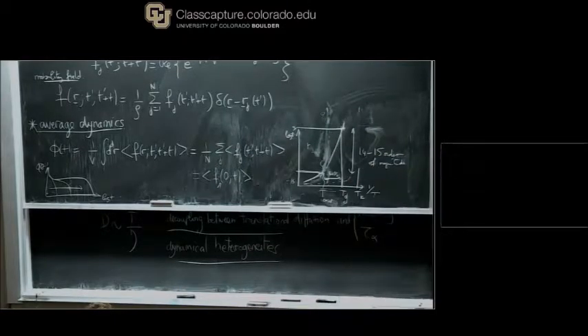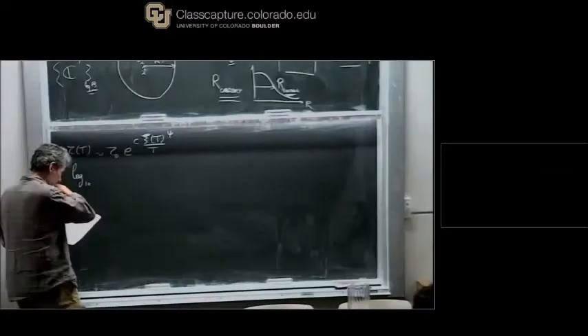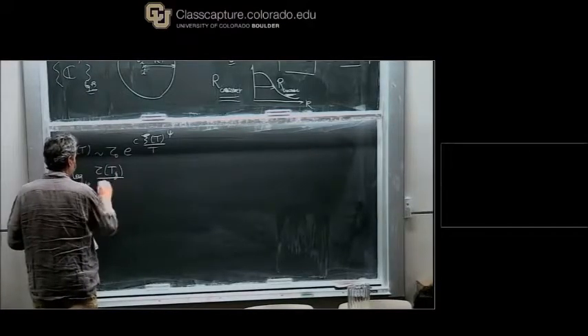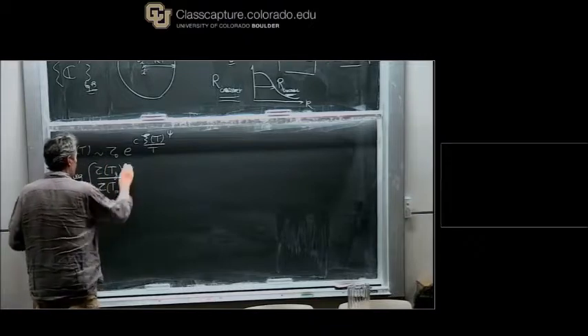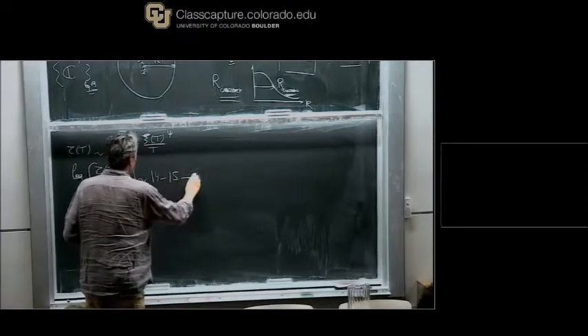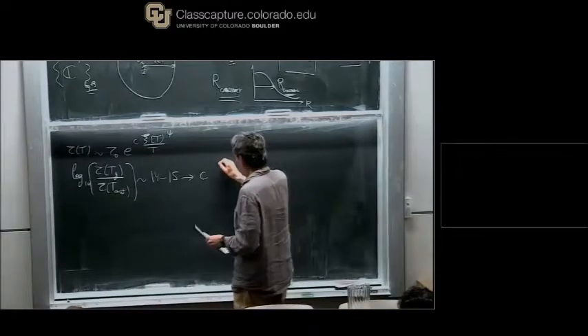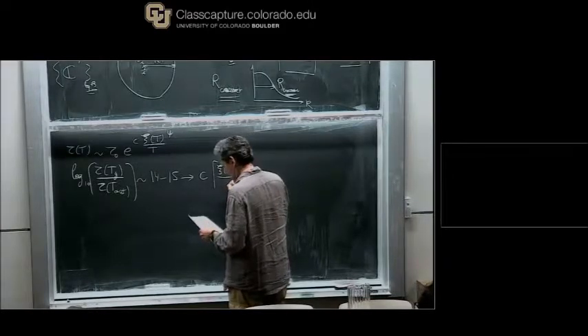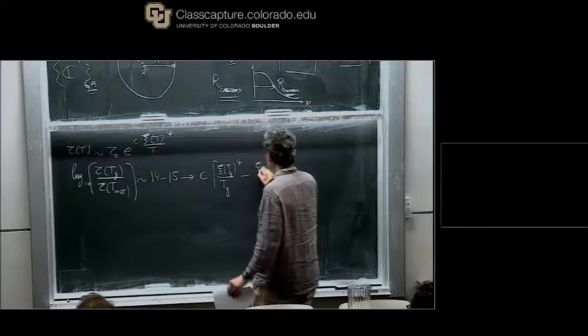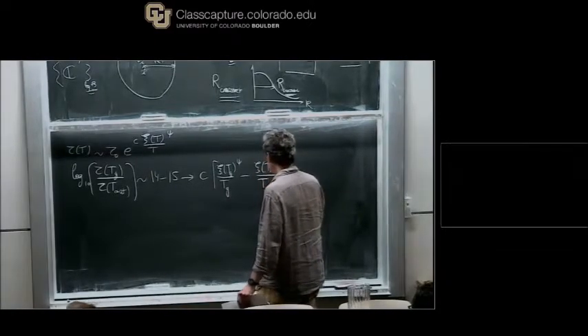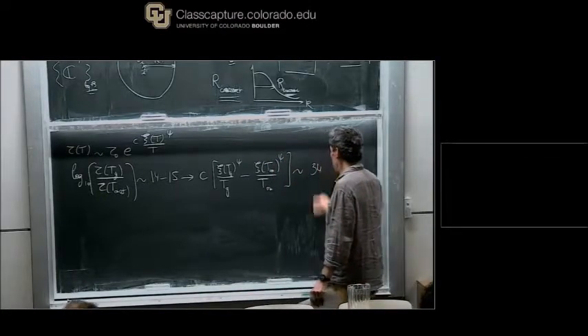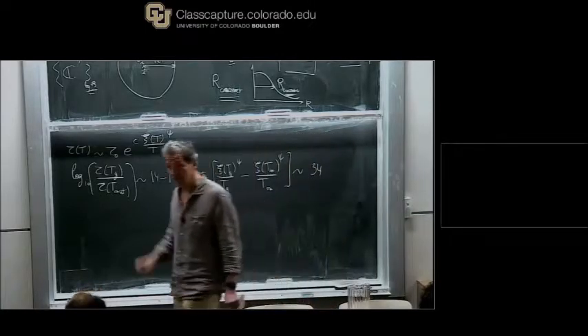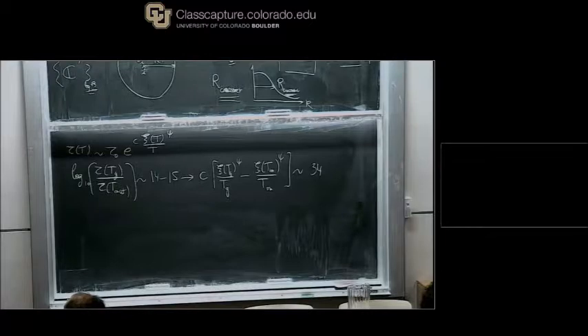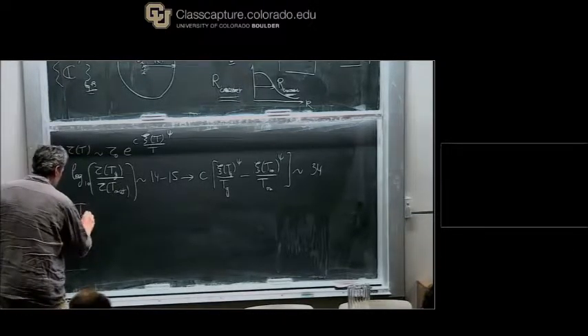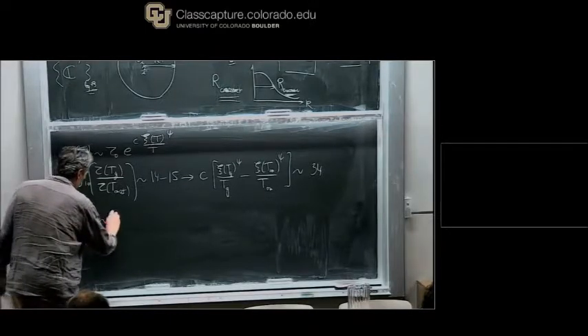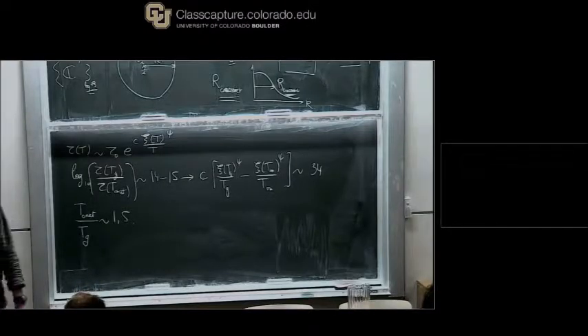Okay, so let's put this. So I know that log 10 of tau at Tg divided by tau at onset, not well defined, but it doesn't matter, is of the order of 14 to 15, which means that C times psi of T over Tg minus psi of T onset over T onset to the psi, is of the order of 34. Now, that's not a big deal. It's just going from log 10 to log e calculation. Okay. Now, as we said, T onset over Tg, let's say, is of the order of 1.5. Okay, this is a typical number.